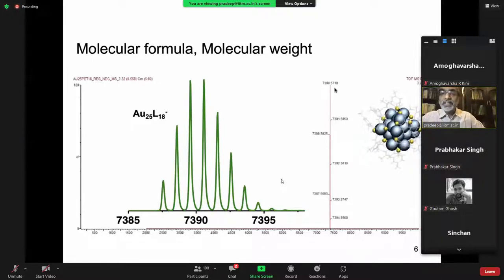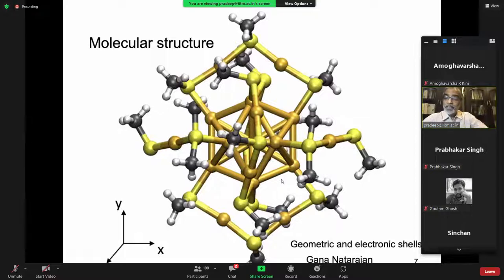So here, the molecular ion gold 25, ligand 18, 1-, is expanded, giving you the isotopic resolution, the peaks that you are supposed to be seeing. Gold itself has only one isotope, 197, but sulfur has four isotopes, 32, 33, 34, and 36. Carbon has isotopes, hydrogen has isotopes, and all of these together give you this beautiful distribution. There are many other peaks, but this is what you see in the mass spectrum in this intensity range.